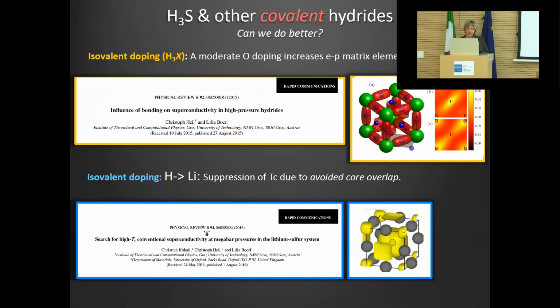If you have the starting point, I mean, the nice thing with the electronic structure is that you can imagine a lot of experiments and try to understand from this experiment. So the first experiment that we did that I'm showing here is one where we said, well, if covalent bonds are so important for superconductivity in covalent hydrides, maybe there is a way to increase the critical temperature, making the bonds more covalent. And we actually found that this is the case. So if one mixes a little bit of oxygen into sulfur, one can increase the critical temperature. If one puts too much oxygen into this structure, actually the structure is destroyed at this pressure because of too strong covalency. There is another kind of isovalent doping that one can think of: if you have H3S, instead of replacing sulfur with something else, one can think to replace hydrogen with something else.